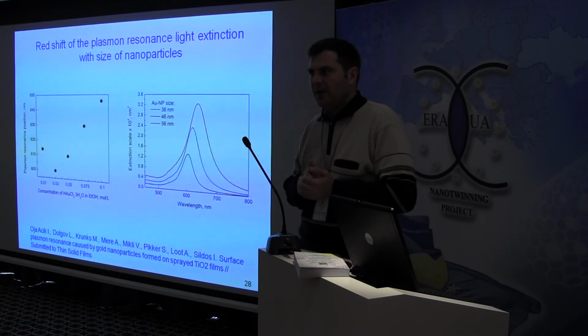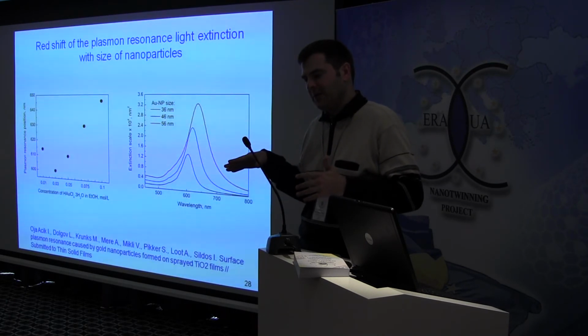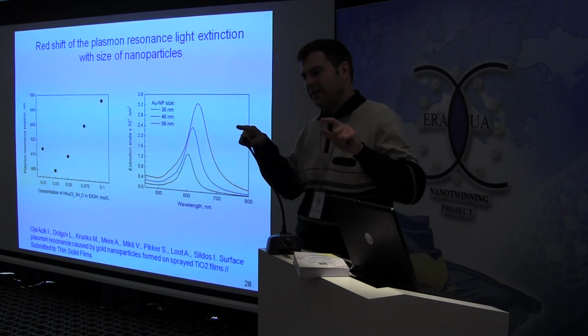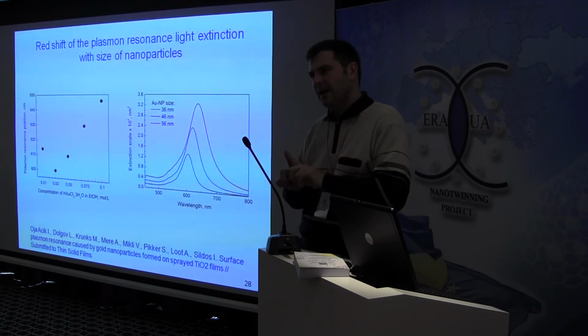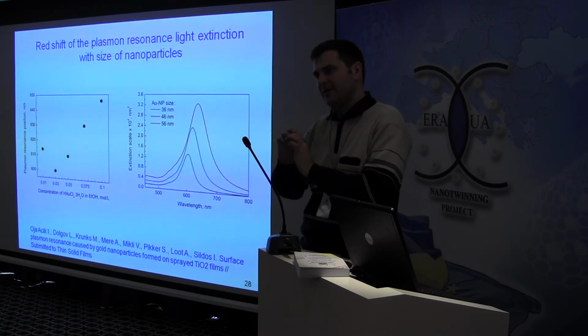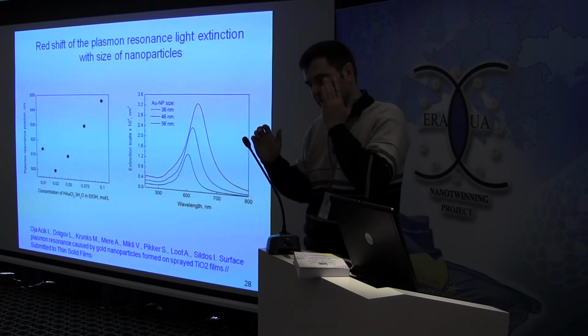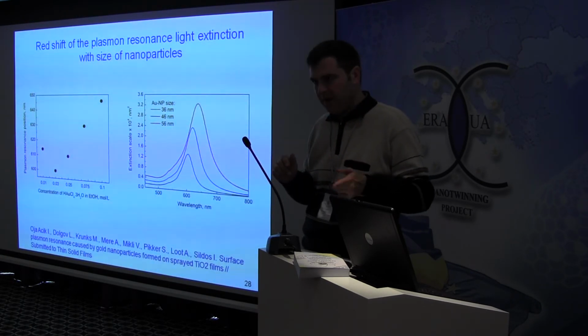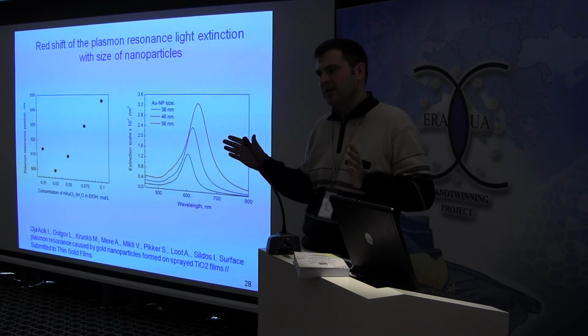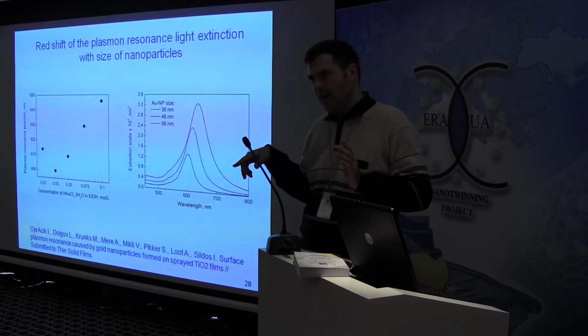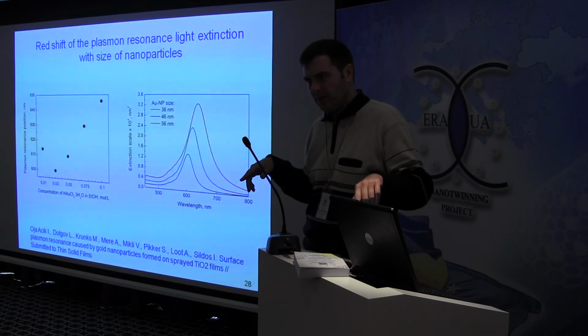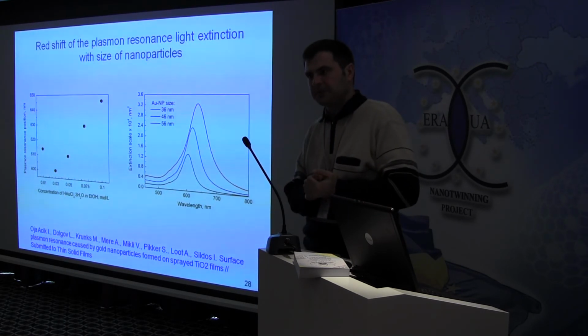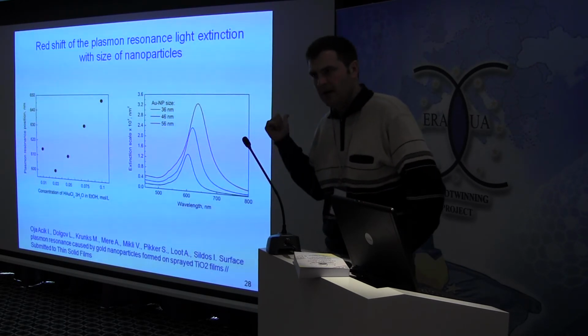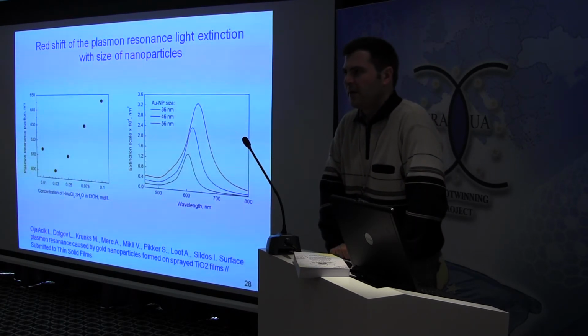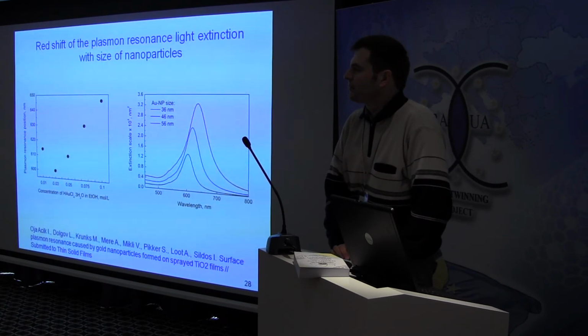Concerning the shift, I tried to model it using Mie calculations, and it is interesting that the higher the refractive index of the environment, the higher the red shift you obtain with increased size. Since here we have a high refractive index medium, like titanium dioxide, near 2.1, I think such a shift can be reasonable. I thought about water, of course. No, it's a high refractive index medium. Okay. Are there other questions?